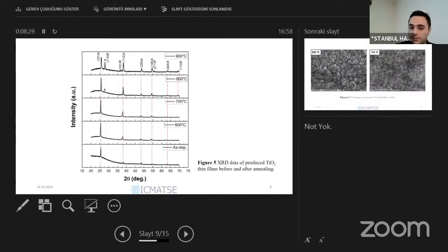Now I'll talk about the XRD. There are 5 different charts. The bottom one is as-deposited, without any annealing. In general, the literature shows an amorphous situation without annealing, but we see at about 25 degrees 2-theta there is a strong and intense peak. This is maybe surprising, but it looks very good for us.